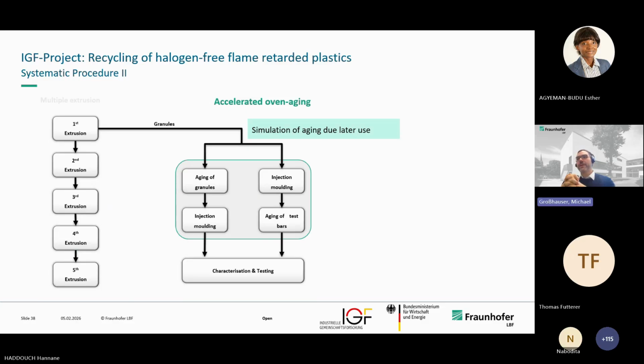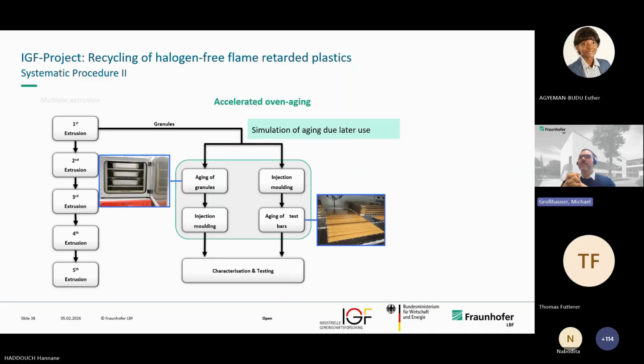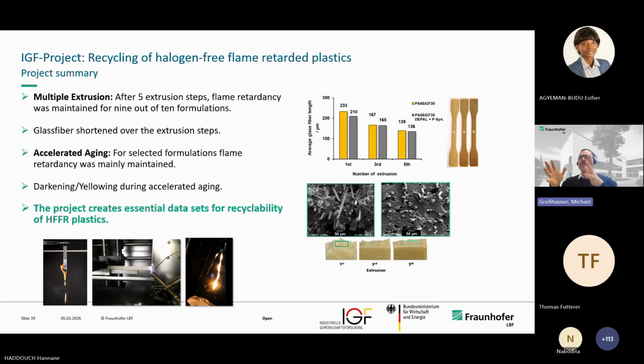Next slide, please. The next thing we did, yes, thank you. And from the first extrusion, we used our compounds, we did an aging, and then we did an injection molding afterwards. So we had, let's say, a simulated use phase in the injection molding materials. And also we did injection molding and we did an aging of the test bars, and also tested the performances of the materials before aging, before injection molding, and so on. So this was for the simulation of the aging due to the using time. Next slide, please.